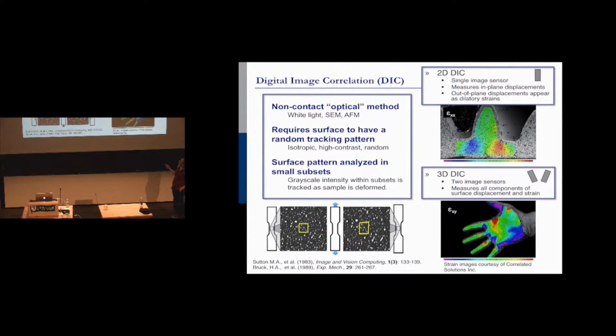And so one of the ways that we look at this is we use something called digital image correlation. And what this is, it's kind of like a next-gen strain gauge. So you can imagine if you had a specimen, okay, and you put 2 dots on it, and you pull it, and you track those 2 dots, it would act as an extensometer, right? So we do that, except we paint the specimen with many, many, many dots. And so we have the specimen, we paint it with a random isotropic assortment of dots, and we draw a box, a subset. And we try to keep the same dots in that subset when we pull.